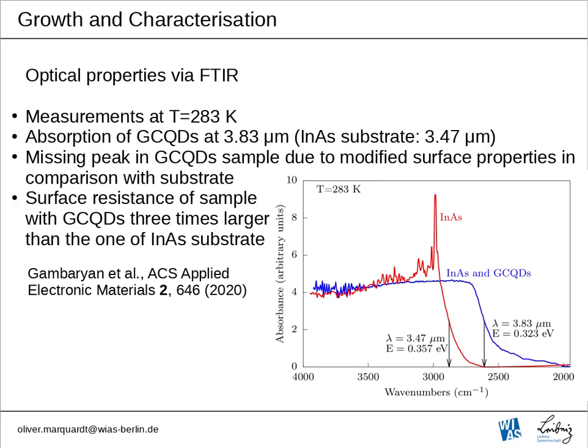The optical properties of our systems were characterized in Armenia using Fourier transform infrared spectroscopy. Measurements were done at 283 Kelvin. What we see is an absorption of the graded composition quantum dots at 3.83 microns, whereas the indium arsenide substrate as a reference has the expected 3.47 microns. Also, there is a peak observed in the reference indium arsenide substrate which is missing in the graded composition quantum dot sample. The reason for this missing peak is certainly that the surface properties of the system with the graded composition quantum dots are significantly modified. Also, the surface resistance of the sample with the graded composition quantum dots is about 3 times larger than that of the indium arsenide substrate reference, which points in the same direction.